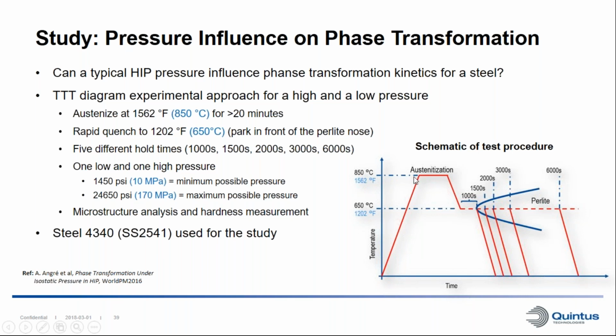So we would heat up the material. We did an austenitization, quenched down, and stopped at the isothermal temperature corresponding to the pearlite nose. Then we held this isothermal temperature for different time periods, so we got a different amount of austenite to pearlite transformation. We did these exact same thermal profiles for low pressure and a very high pressure in the HIP, and then compared the results by microstructure analysis and hardness measurement.